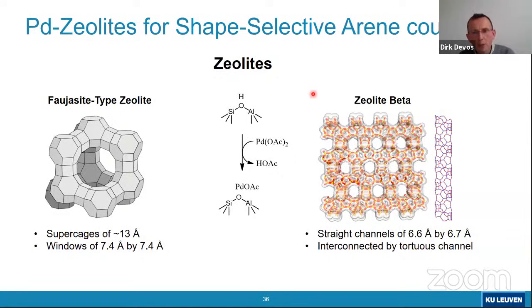It's always going to simplify the workup, but actually it turned out that there were quite some other effects going on. The idea that we have about the active site in all these reactions, just to make life easier for you, and we have a lot of evidence for that, and I will show some of that evidence, is that basically what is active in these reactions is a palladium originating from palladium acetate. But in fact, the palladium acetate, which is trimeric but could be monomeric and so on, reacts with an acid proton in the zeolite. The result is that one of these acetate ligands is protonated again, so it leaves the zeolite. The palladium is then sitting on the zeolite with one acetate ligand still on the palladium, and the other charge for the palladium II is actually compensated by the lattice. That's the basic idea of how we think the active site could often look in these materials.